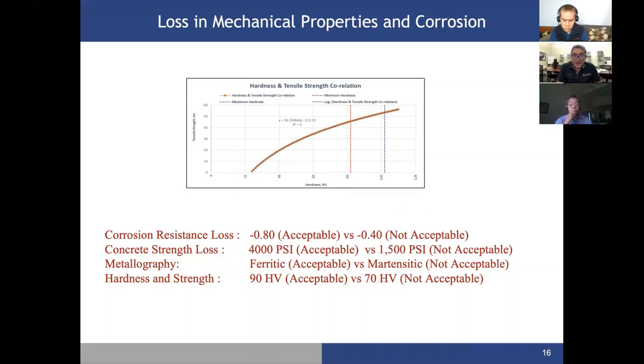A 4,000 PSI for concrete compressive strength is acceptable. But if you do the measurements after wildfire exposure, you get 1500 or lower, it's not acceptable. Metallurgically, if you do a non-destructive metallurgical evaluation, ferritic, pearlitic structures are acceptable. Martensitic structures are not acceptable because it indicates you have loss of ductility. You have embrittlement in place that upon impact, you can have cracking and failure.